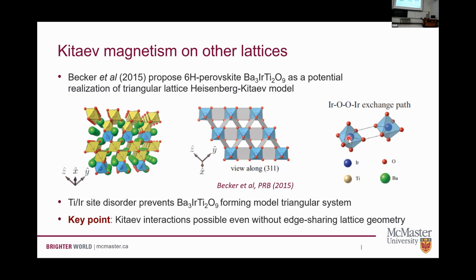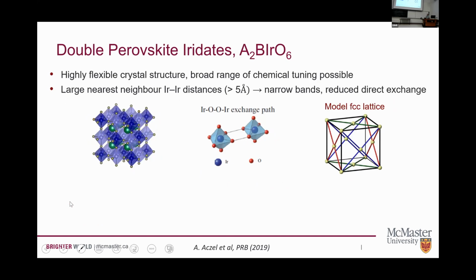So for barium iridium titanate, this didn't actually work out very well. It turns out that the titanium and iridium are fairly close in size, and so they mix, and the site disorder prevents this from being a nice model triangular system. But it opened up this idea that you could get Kitaev interactions even without a honeycomb lattice. And so one place that you can go where you still have these sort of parallel edged octahedra is to the double perovskite structure. Okay, so this is another crystal structure we know and love here.